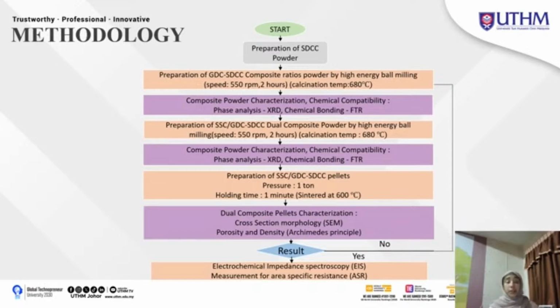So next is the preparation of SSC, GDC, SDCC dual composite powder by high energy ball milling, and it is a repetitive process using the same ball milling process. The speed is still the same, the duration also, and the calcination temperature is the same. It is maintained at 550 rpm for 2 hours, and a calcination temperature of 680 degrees Celsius. And the same repetitive process involves the composite powder characterizations, chemical compatibility, which is XRD, and also FTIR, chemical bonding and phase analysis.